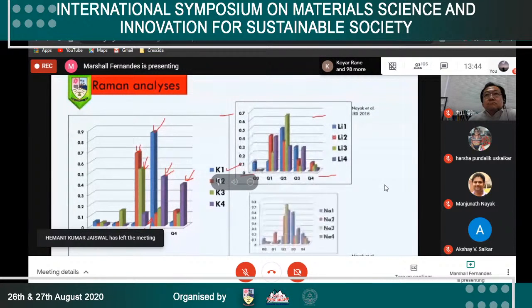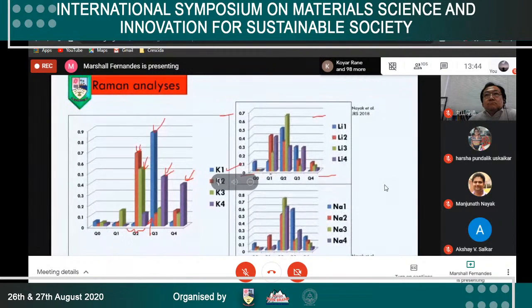Comparing this to the data of the lithium-based and sodium-based samples, we see that the lithium samples have open structures with major contributions of Q1 and Q2, and also good contributions of Q2 in the sodium-based samples. Now, lithium-based glasses are known for fast ion conduction, and similarly, sodium-based glasses are studied intensively for their conduction property as a replacement to lithium-based glasses. If we compare the open type structures of the lithium and sodium-based samples to the potassium samples, there seems to be a good scope for K2 and K3 based samples as a good electrolyte material. Of course, this is subject to the outcome from the conductivity studies to be carried out soon.